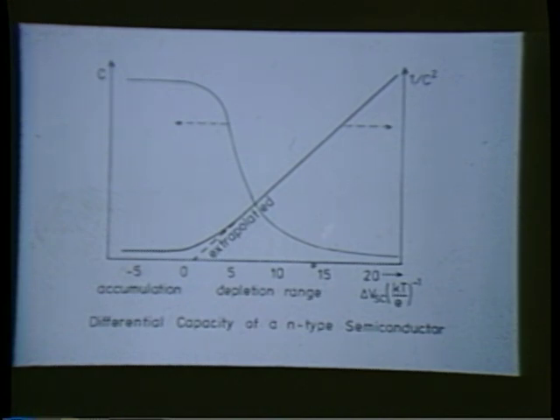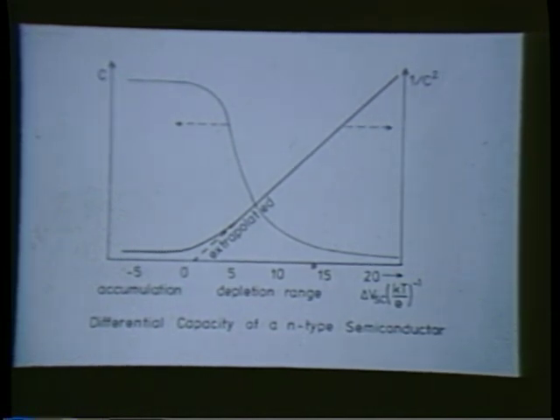This part of the capacity curve can be used for a determination of the zero point of charge. The theory shows that it should follow 1 over C squared, the Mott-Schottky relation, against the potential, which should give in the extrapolation the point where we have no excess charge on the surface. That is called, in the case of the semiconductors, the flat band potential, because then the energy of the band edges is flat from the bulk up to the surface. That's a well-known relation known from solid state physics and can be verified also in electrochemical systems.